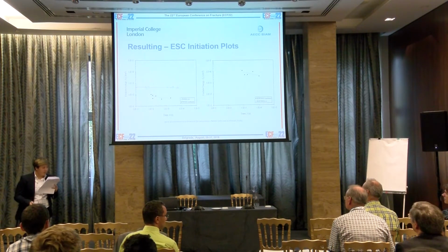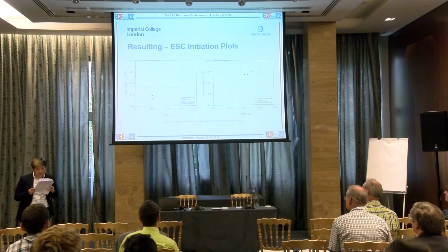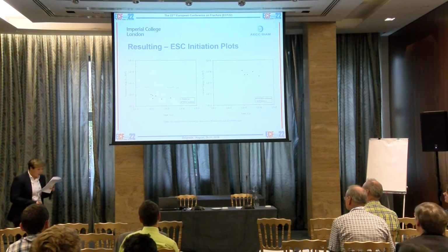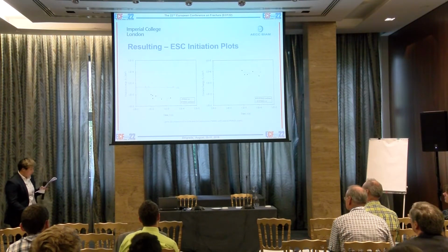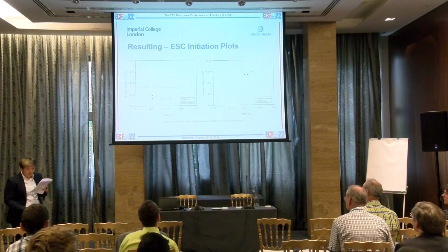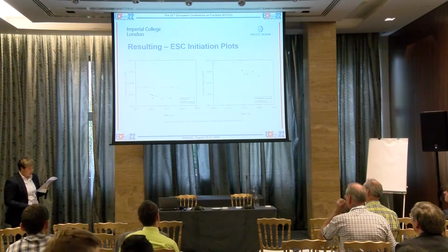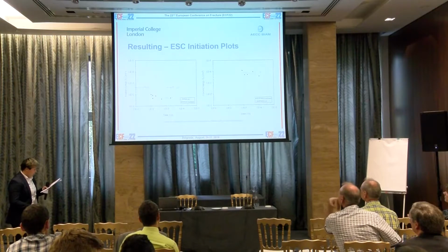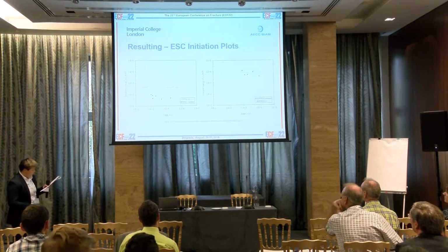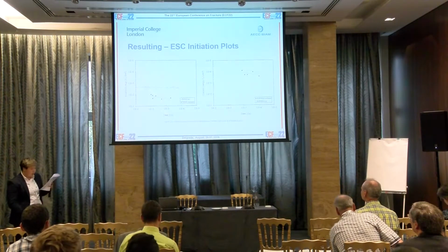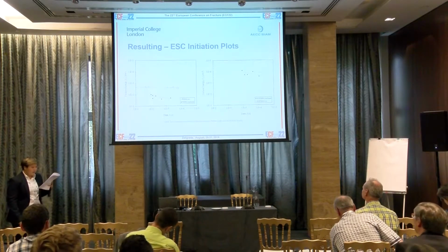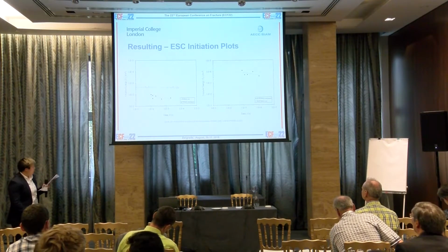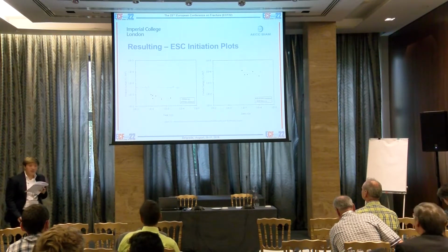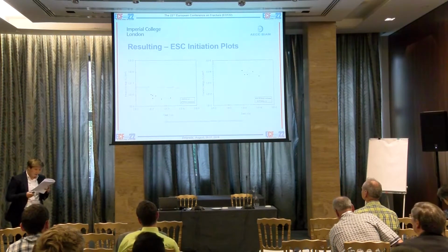The crack blunting effect may dominate at high crack speed, resulting in a crack tip radius exceeding a critical value. As a result, the crack growth will pause under constant load condition unless more energy is applied to propagate the crack. And as suggested from the amorphous PMMA result, the initial load and therefore the initial fracture energy applied to the specimen in methanol are significantly lower than those performed in air.